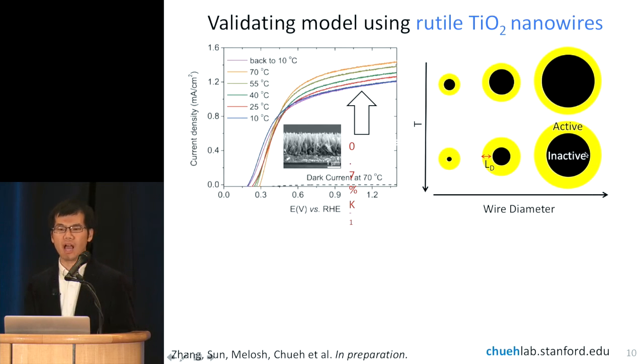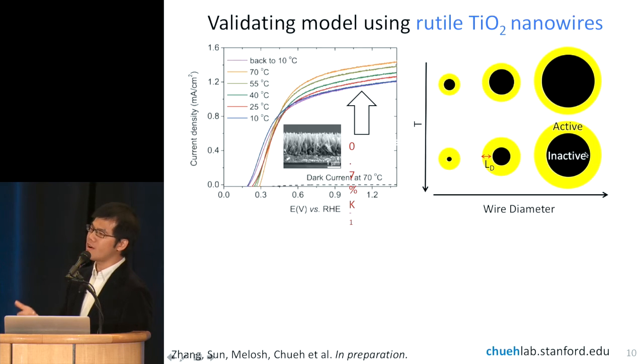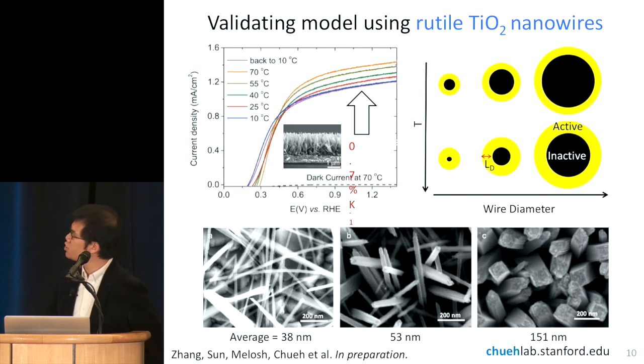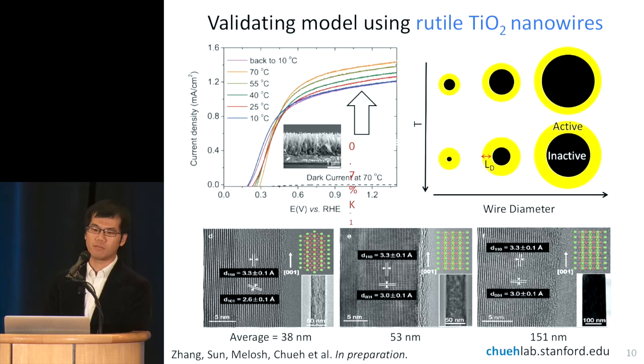So simply by using geometry, varying temperature and the wire diameter at the same time, we can try to test our theory that it is the light absorption competition between the space charge region and the minority carrier diffusion region that's controlling the performance. And this is just to show you that we have fabricated three different diameter nanowires, and to convince you that the surface of these nanowires are the same, we carried out high resolution imaging on the electron microscope just to confirm that the termination layer where the titania intersects with the liquid is in fact the same. So the difference between the three wires is only the diameter, okay?